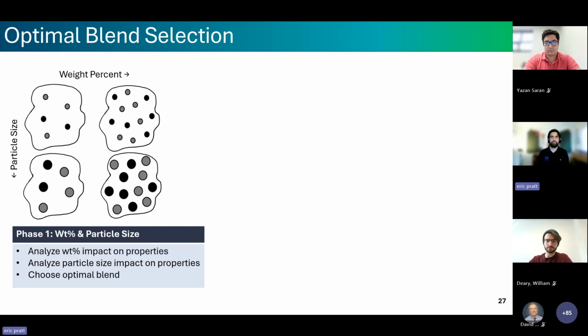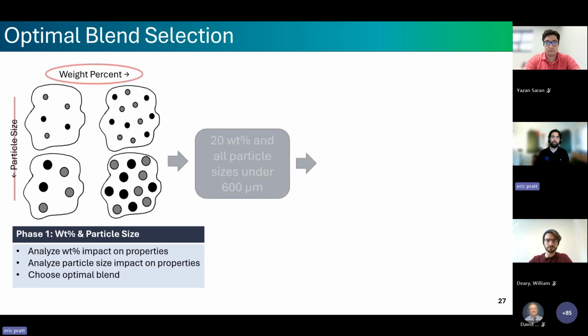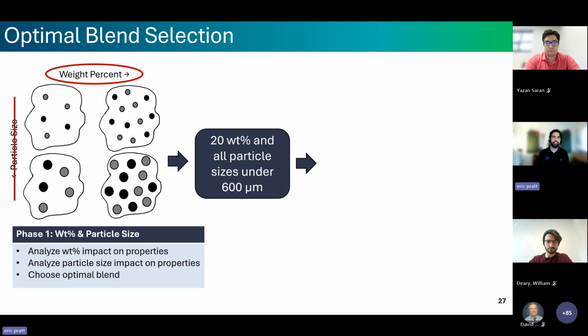So to put all three tests together, the decision becomes fairly clean. Melt flow index turns out to be our more restrictive of our two critical constraints, capping loading at 20 weight%. Particle size, meanwhile, only meaningfully affects tensile behavior, which isn't a governing property for this application. And its influence on impact and processability starts to disappear well below the 20% ceiling. So our optimal formulation that we chose was 20 weight% XLPE with no restriction on particle size below 600 microns.